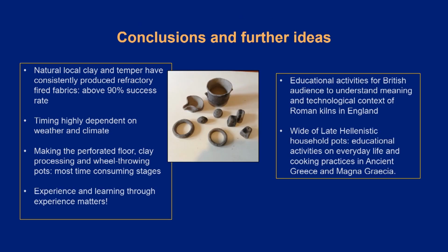Despite the problems, we can draw some conclusions from what we have done so far. The clay and temper collected in the area of the experiment's place had above 90% successful firing rate in more than 10 gas kiln tests and pit firings. The timing of the stages of the chaîne opératoire of pottery production and kiln building largely depends on seasonal and geographic climate. Making the perforated floor, clay processing and wheel throwing were the most time-consuming stages of the operative sequence.